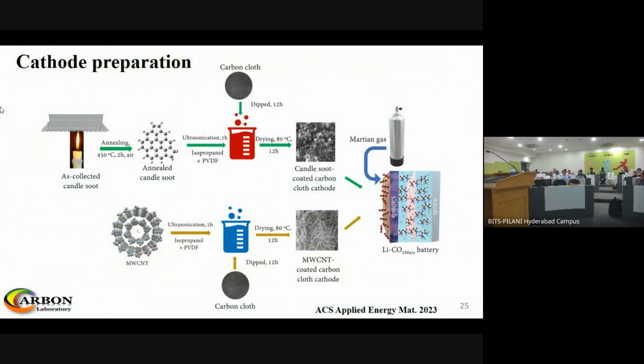So here we have collected the candle soot like this, and did the annealing. This annealing is done further to ensure that there is no impurity remaining. And this annealing also increased the surface area a little bit, from 100 to, let's say, 150 meters squared per gram. And then we did the ultrasonication in isopropanol with PVDF, made a solution of it, and deposited it on the carbon cloth, which is used as a substrate, catalyst support. And this candle soot was used as a simple catalyst.